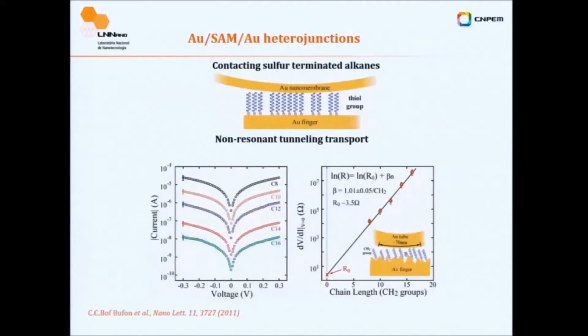So our first work was simply repeating what people have done in the past years, simply characterizing alkanethiols. What we should expect when you contact, if you change the number of carbons, you should see tunneling behavior, direct tunneling. And we did this with different chain lengths, quite a beautiful curve. It's an exception, in general, you know this, those that measure cannot get such a nice curve.